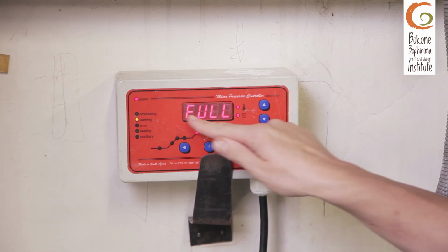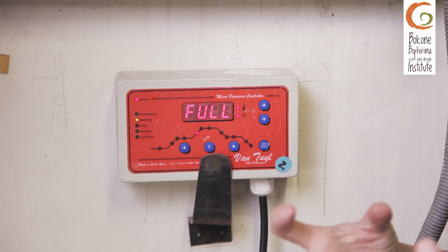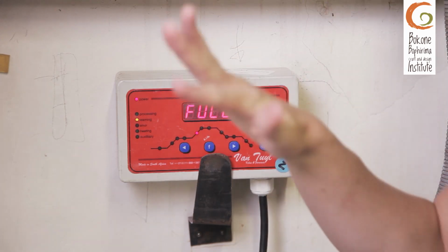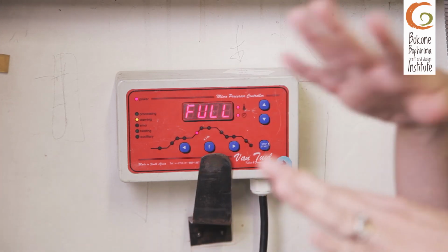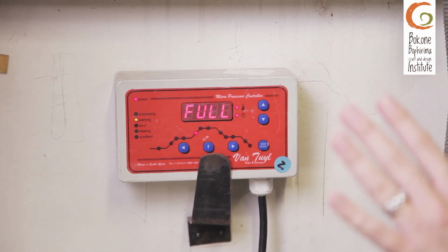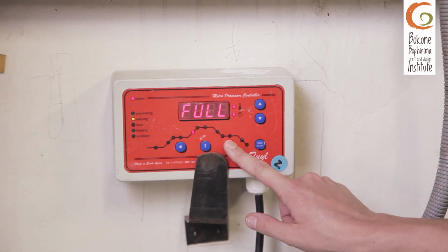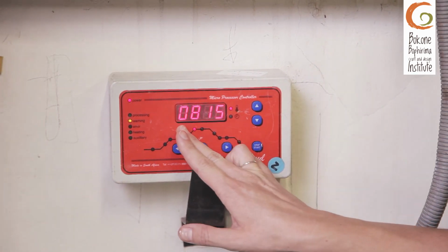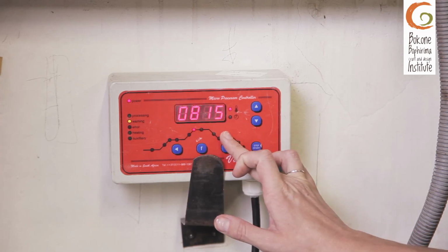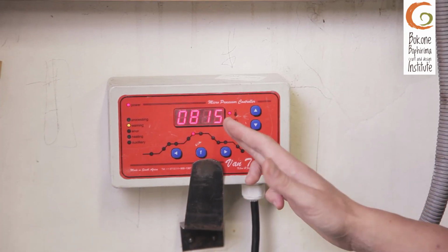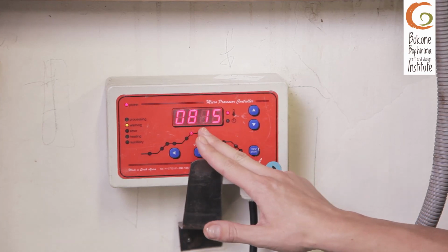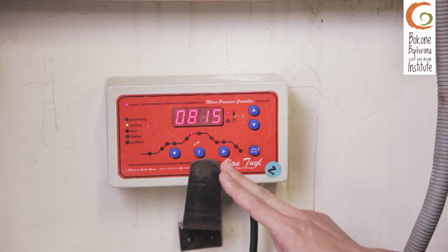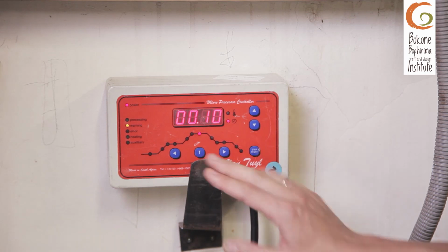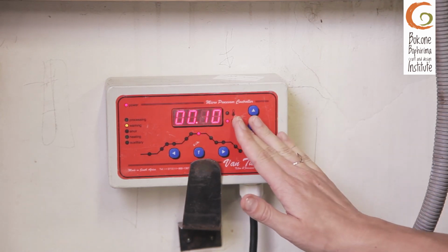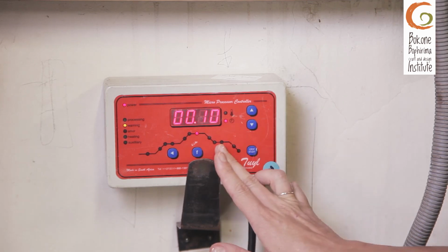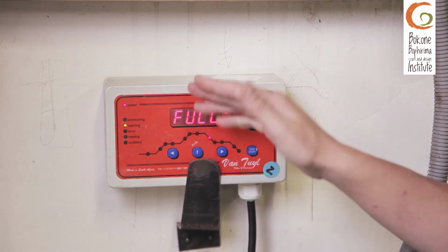So what full stands for, basically, it's telling me that I want my glass to ramp up as fast as possible, or sometimes it may mean as fast down as possible to cool to a certain point. So I want my glass to go as fast as possible up to my top temperature, where I'm working with 815, which is, according to my test pieces, my desired top temperature for my high temp enamel paints. I'm then going to allow it to soak for 10 minutes. 10 minutes is sufficient for this firing, and then I need to now crash cool.